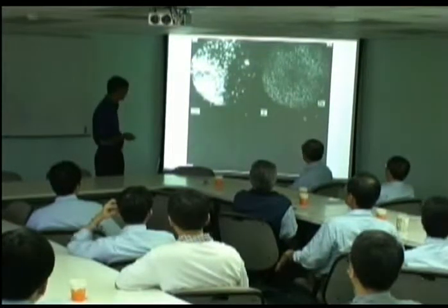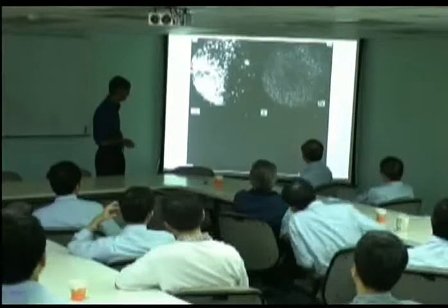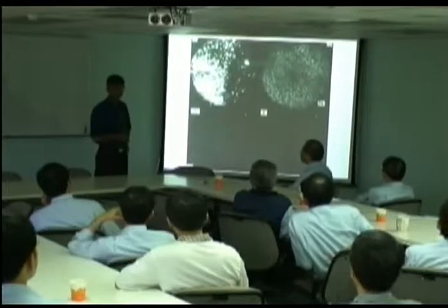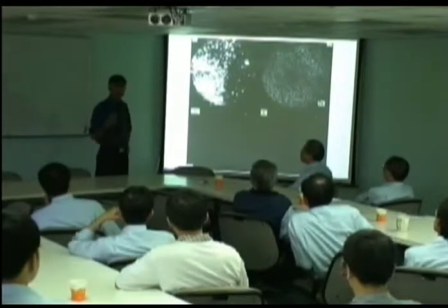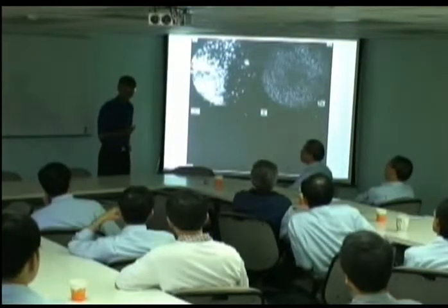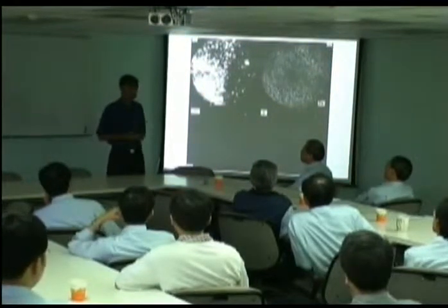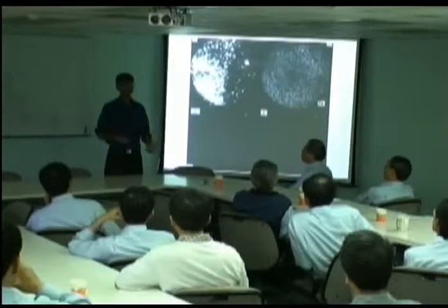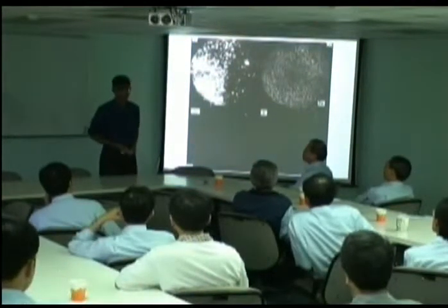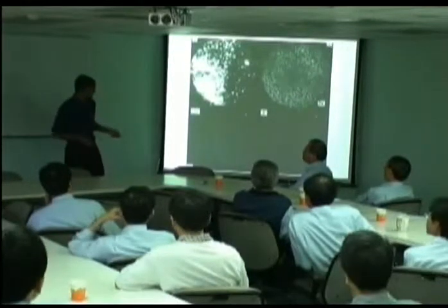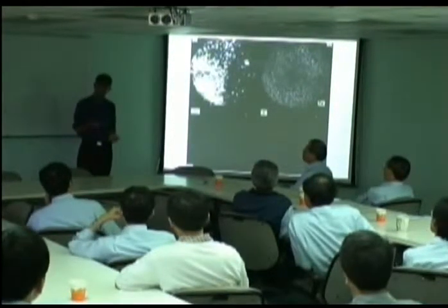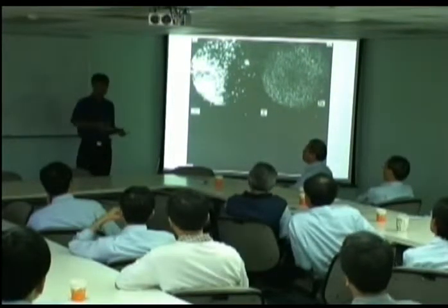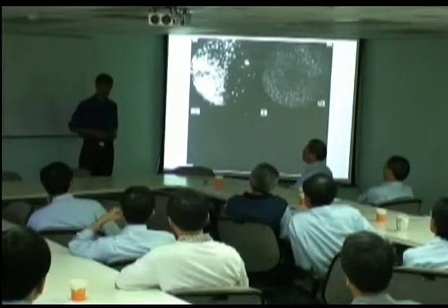But look what's happened to carbon. Can you see that the carbon has partitioned into the austenite? There's almost no carbon on this side. Okay. So, do we conclude from this that carbon diffuses during the bainite transformation? Or is it the case that the carbon has moved after the bainite is formed? So we need to investigate that, because carbon has a very high diffusion coefficient, and it is possible that it has partitioned into the austenite after diffusionless growth.